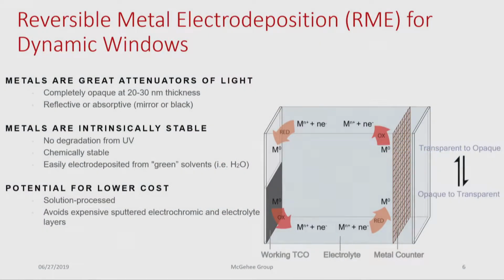So again, metals were such attractive choices to us because they have fantastic light attenuation properties. It's estimated that you only need about 20 to 30 nanometers of a completely conformal, smooth metallic film to substantially block out a lot of light. Additionally, metals are rather stable, especially towards UV. Another great benefit is that metals can be very easily solvated and electrodeposited in what we call green solvents, something along the lines of water.